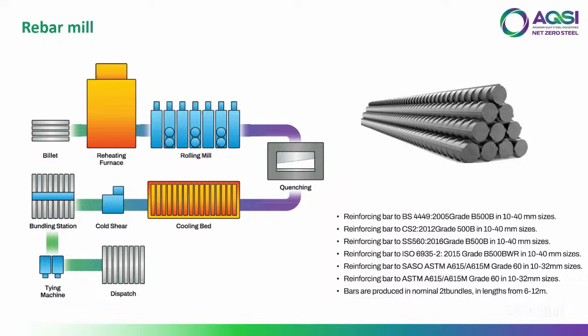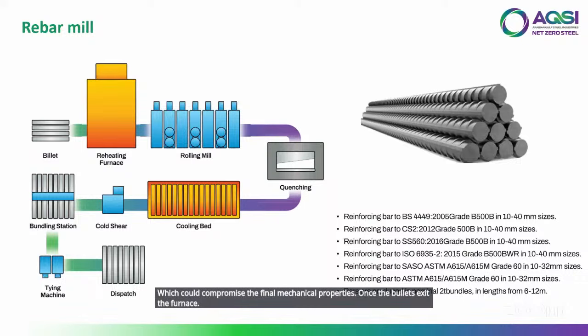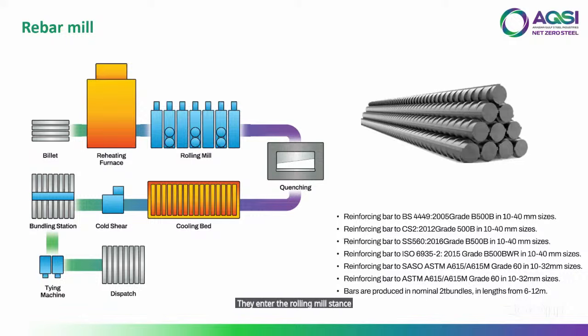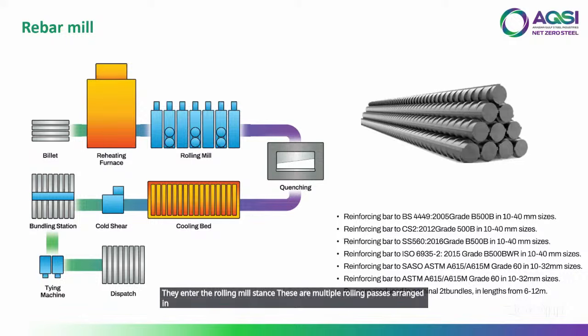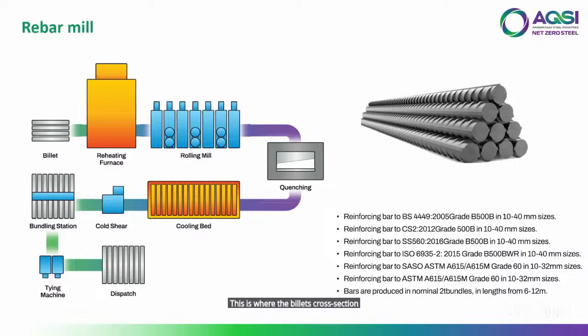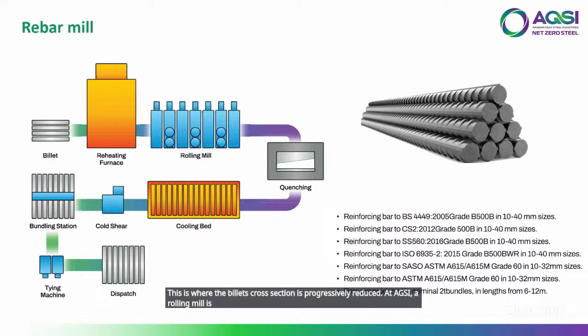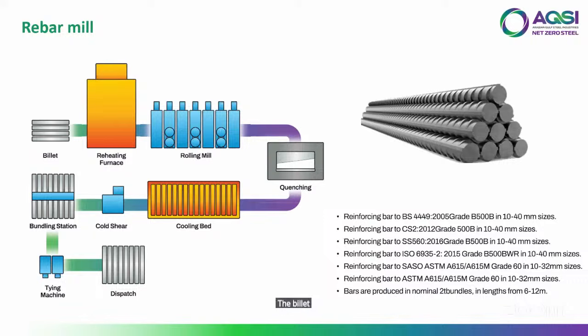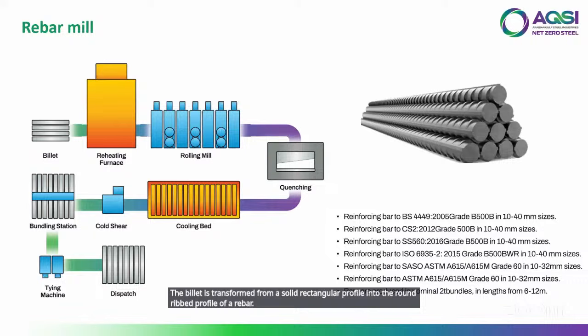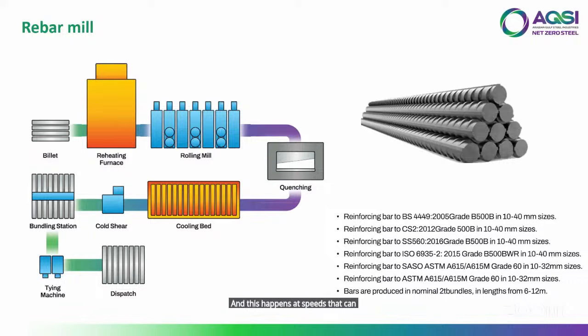Once the billets exit the furnace, they enter the rolling mill stands. These are multiple rolling passes arranged in sequences of roughing, intermediate, and finishing stands. This is where the billet's cross-section is progressively reduced. At AQSI, our rolling mill is designed for high throughput and dimensional accuracy. The billet is transformed from a solid rectangular profile into the round ribbed profile of a rebar. And this happens at speeds that can exceed 15 meters per second.